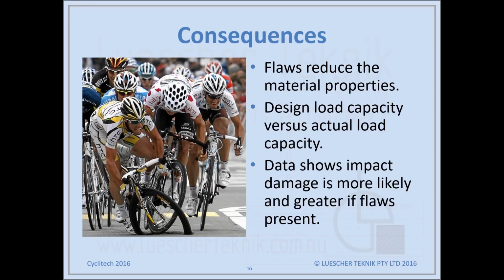So one of the things that we've seen a lot over the time is that if there are flaws in the part, even a lower level impact can lead to greater damage within the part. So by avoiding these flaws or handling damage or any of these sorts of aspects, you get better life out of the part, better durability out of the part, and higher safety out of the part.